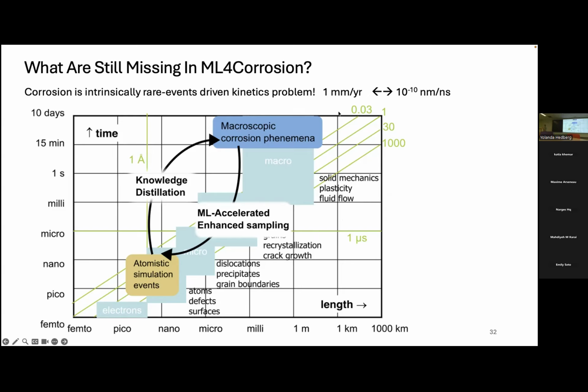One thing I eventually want to mention is, if you think about the corrosion rate in millimeters per year, and you convert that to how many atomic layers can be removed per nanosecond. A nanosecond is a typical time scale for molecular dynamics simulation. If you compare these 2 time scales, you see that a corrosion rate of about 1 millimeter per year is just 10 to the power of minus 10 nanometer per nanosecond. So basically you can never see the real corrosion event in a molecular dynamics simulation. These events are a rare-event-driven scenario. Unless you do a lot of configurational space searching and atomistic events, we are not able to fully answer these questions without combining these two regimes together.